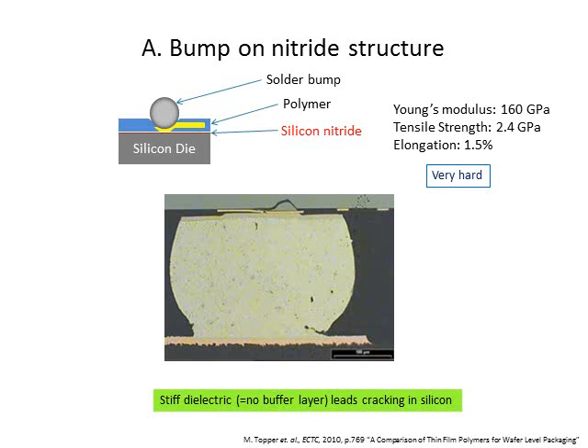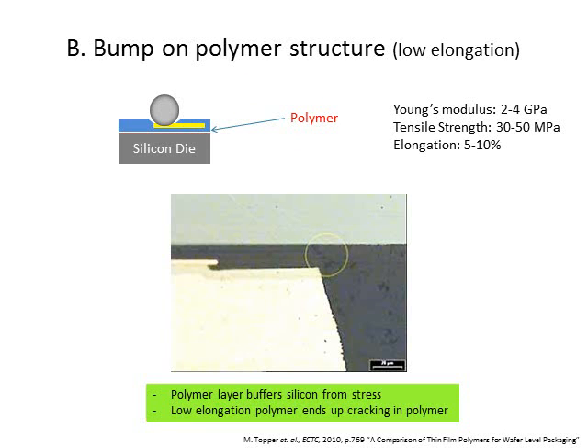Silicon nitride is known as a very hard material, as indicated in this slide. And in this structure, the cracking mode is a propagation of the crack in the silicon, and this cracking mode is not desirable. Therefore, to overcome this issue, the so-called bump-on polymer structure has been developed. In this structure, polymer is introduced in between the silicon die and conductive layer. And this polymer layer acts as a stress buffer layer, and silicon cracking is prevented.